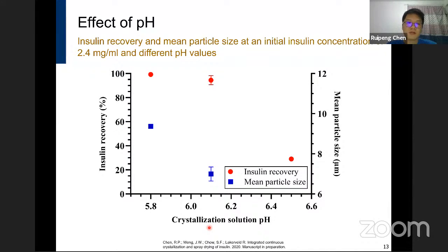We can also look at the effect of pH on the insulin recovery and the mean particle size at the initial concentration of 2.4 and different pH values. The highest recovery was obtained at the lowest pH, which has the highest supersaturation. This is because the highest supersaturation has the fastest nucleation rate, and therefore the supersaturation is consumed more rapidly. And the larger particle size was obtained at pH 5.8 compared to pH 6.1, and we think this is because of the agglomeration as observed on both the microscope and SEM.